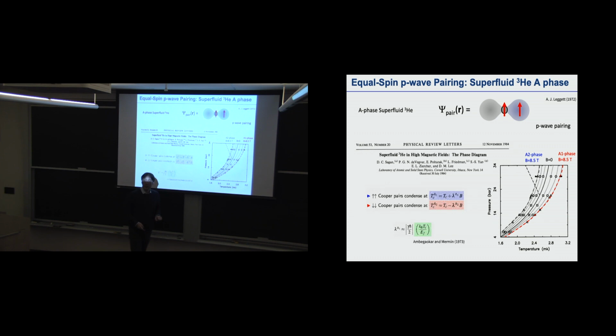An interpretation of this kind of behavior is indeed that this is a Cooper pair made with the same spin, right - either spin aligned with the magnetic field, or spin anti-aligned with the magnetic field. Because of the Zeeman effect, one of the Fermi surfaces becomes large and the other becomes small, and the size of the Fermi surface is of course tied with the density of states.